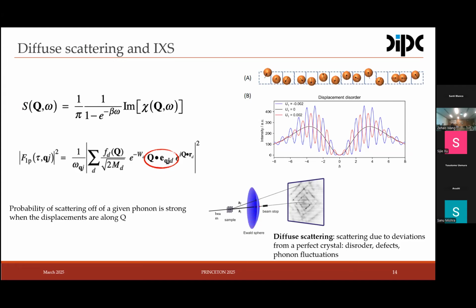And on the other hand, this technique allows us to distinguish the primary order parameters in these multiple Q charge order materials. We know that diffuse scattering may appear due to deviation from a perfect crystal, like defects, vacancies, and so on. In our case, we assume that our samples are not perfect, because in reality there are no perfect samples, but the disorder and the number of defects and vacancies in our samples are essentially minimum. We don't want to deal with bad samples.